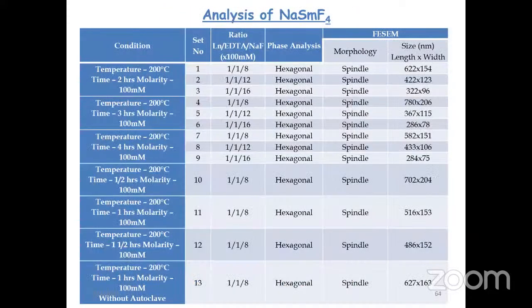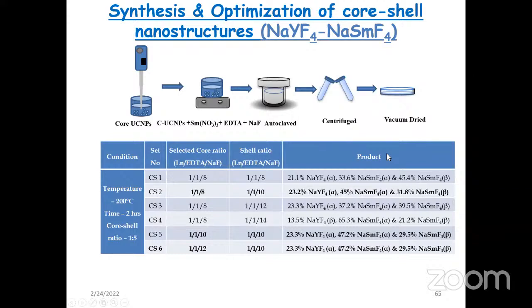Here we could find a spindle-like morphology in all the cases, by varying the temperature, the concentration and the exposure time. In every case, we found the formation of a hexagonal phase, but we wanted to optimize the size. So at a lower concentration, at 200 degrees Celsius, we were able to produce a hexagonal phase with a lower particle size.